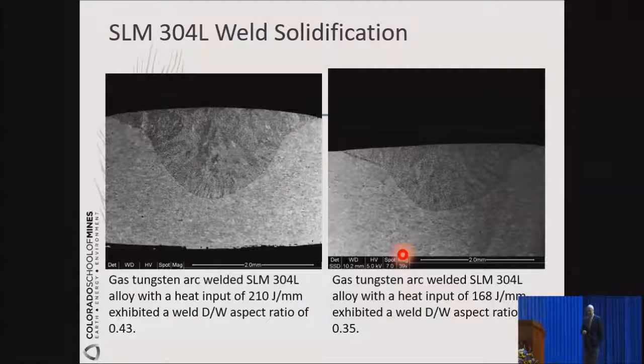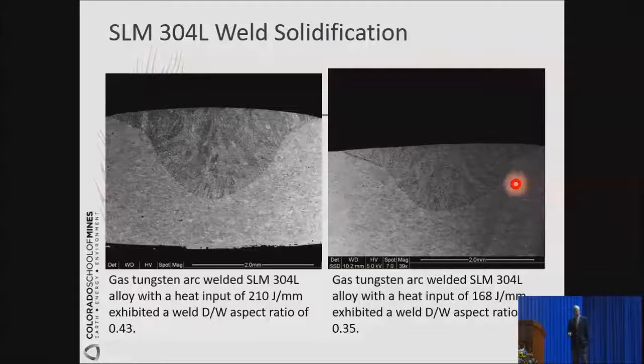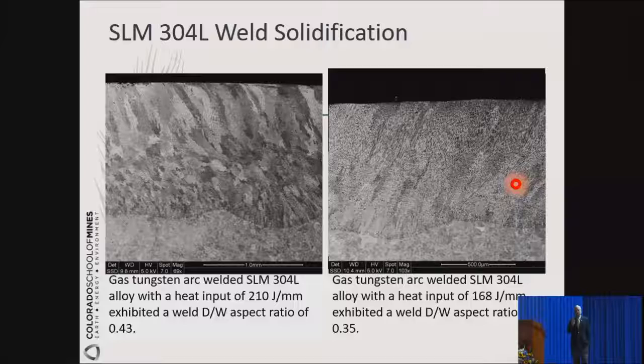Okay, all right. So look at this. These are gas tungsten arc welding, over the selective laser melting, which is powder bed fusion in this case here. The morphology is different by changing the heat input as well. So the aspect ratio is 0.43 on the left and 0.35 on the right. And if you look at the longitudinal transverse cross section, look at the bottom of the bead. It has a lot more of these fluctuations. It's not quite like the laser spikes or the electron beam spikes in the welding, but it does show that difference.